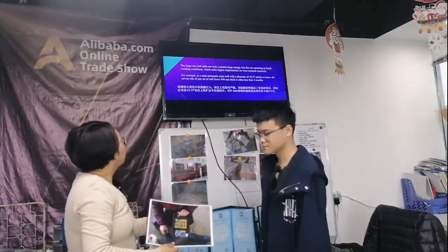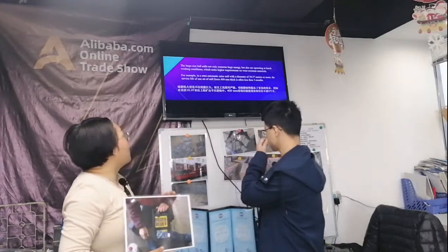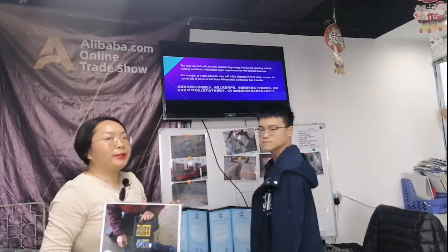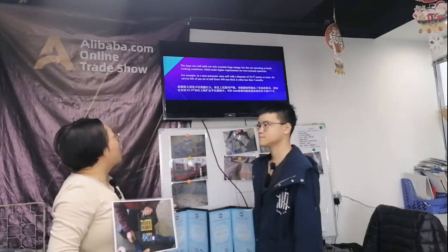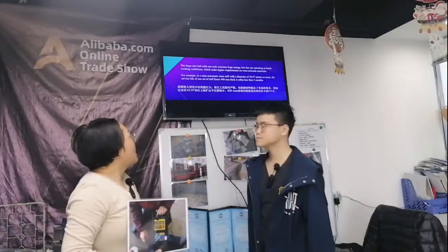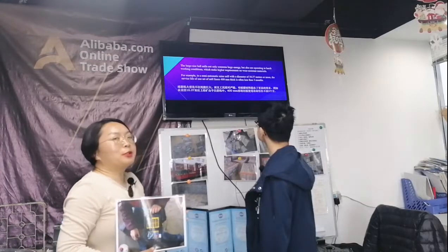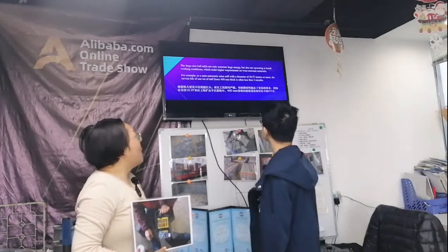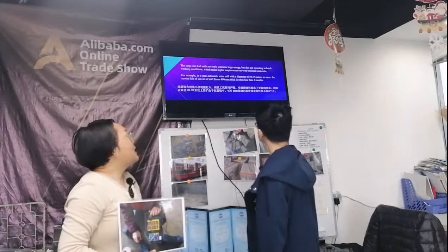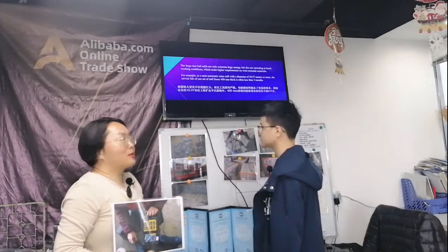Okay, thank you. So let's move to the next page. The large size ball mills not only consume huge energy but also are operating in harsh working conditions, which make higher requirements on wear-resistant materials. For example, in a semi-autogenous mill with a diameter of 10.37 meters or more, the service life of one set of mill liners 400 millimeters thick is often less than 3 months. Very short service life.